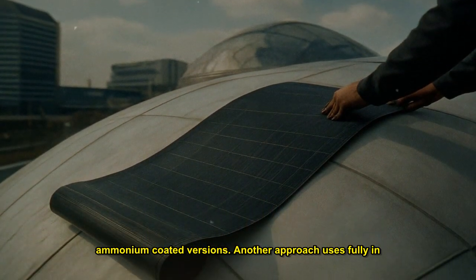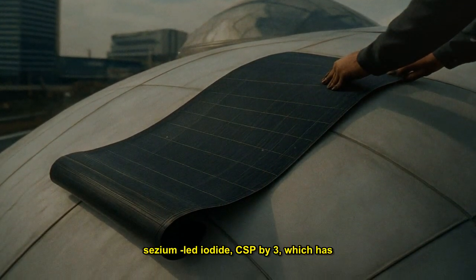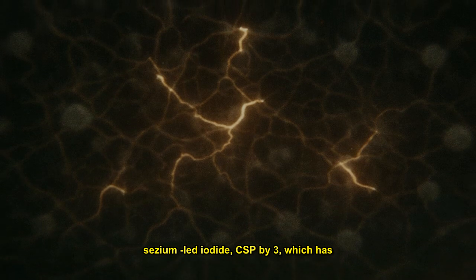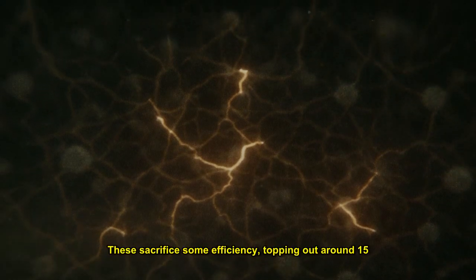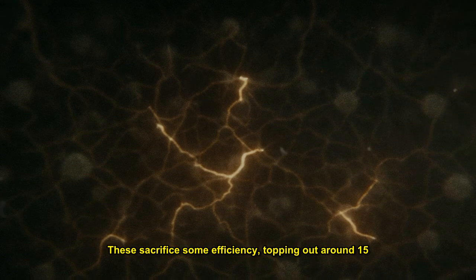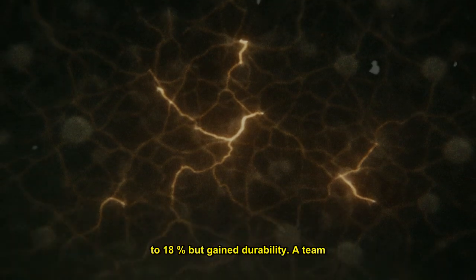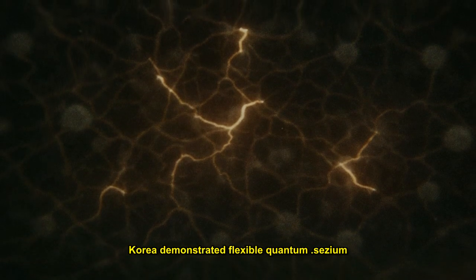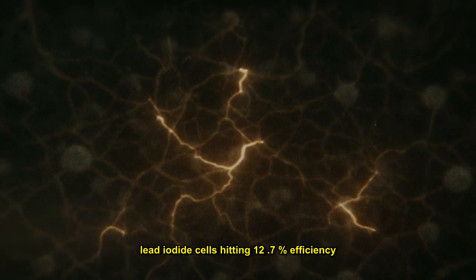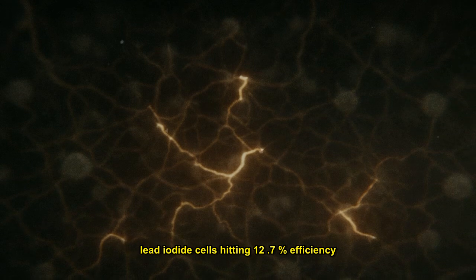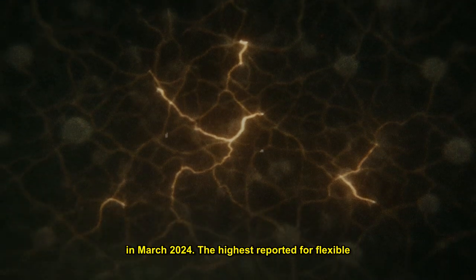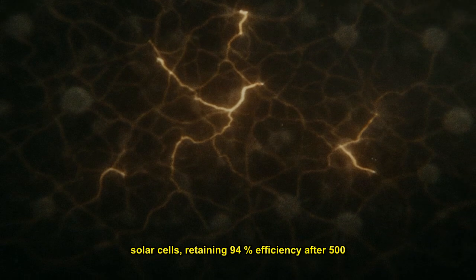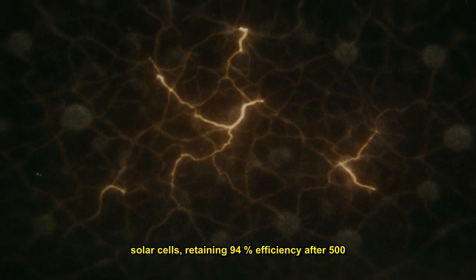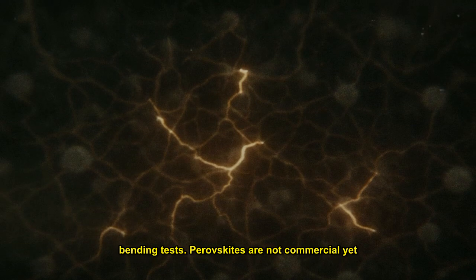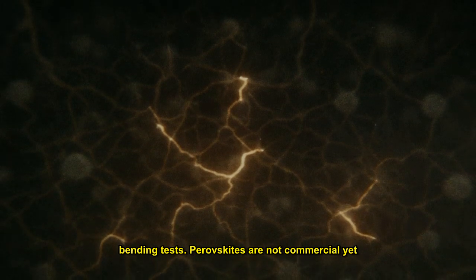Another approach uses fully inorganic perovskites like cesium lead iodide, CsPbI3, which has no organic cations to degrade. These sacrifice some efficiency, topping out around 15 to 18%, but gain durability. A team from Hanyang University and Kookmin University in South Korea demonstrated flexible quantum dot cesium lead iodide cells hitting 12.7% efficiency in March 2024, the highest reported for flexible quantum dot solar cells, retaining 94% efficiency after 500 bending tests.